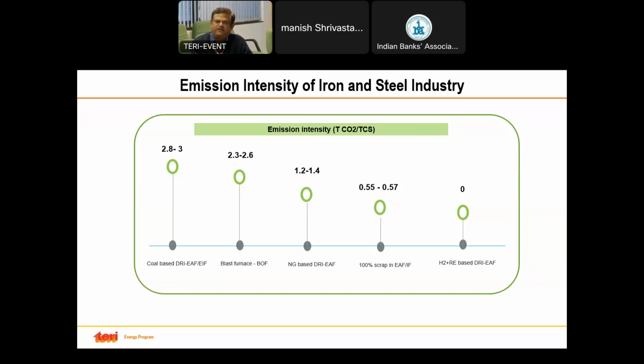Then the fourth bar, you can see 100% scrap in electric arc furnaces and induction furnaces, which is one of the lowest that we can see. This is the steel scrap received from various end user segments like automobiles or construction sectors. If 100% scrap is used, then the emission intensity is around 0.56.